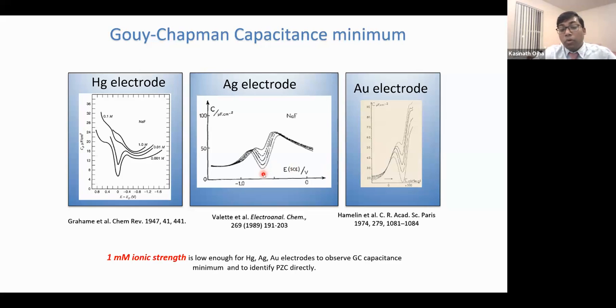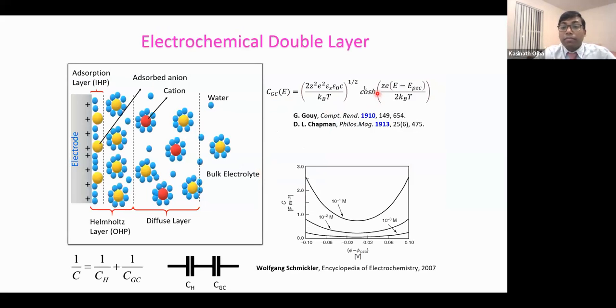And why should we go for low electrolyte concentration? Now, if you look at those equations here, once the concentration is very low, at that time you see a minimum, because CH will be much higher than CGC, so 1/CH will be kind of negligible. So the total capacitance of the system will be equal to the Gouy-Chapman capacitance. Once you make it a low concentration, CGC is a smaller value, but CH is much higher, so that goes like negligible. But at high concentration, CGC becomes super high, and then we only see the Helmholtz layer capacitance.